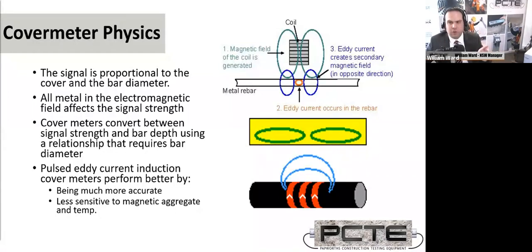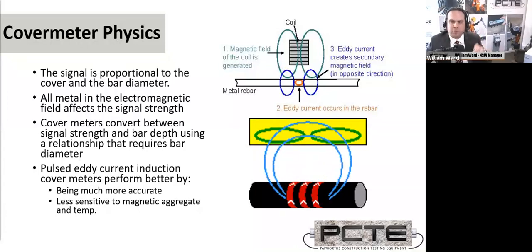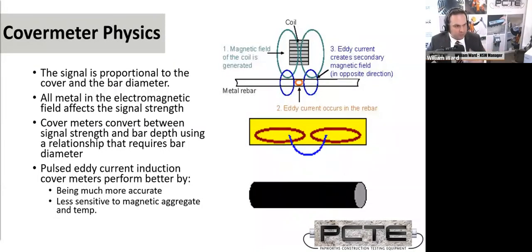And that probe is going to produce an alternating current electromagnetic field, which is going to in turn induce an alternating current in the reinforcing steel. The current flowing through the reinforcing steel produces its own electromagnetic field. So by turning off the measurement on that field, we can then determine the signal strength of the pulsed eddy current induced field. And that's what cover meters measure.